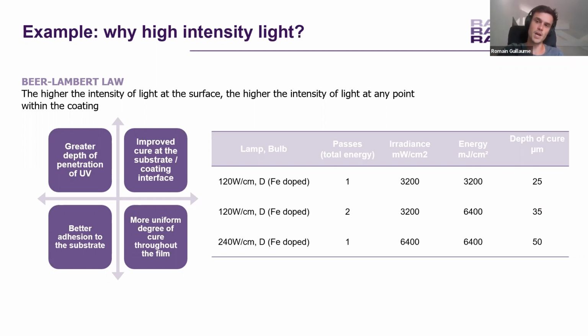But now, for the same energy, if I go to the third line, I'm taking a lamp which is 2 times more powerful, and I'm going below it only 1 time. The irradiance is 6,400 milliwatt per square centimeter, so 2 times the irradiance of the previous lamp. So I have a higher intensity. At the end, my energy is equivalent to the second line: 6,400 millijoules per square centimeter. But for the same energy, I had a higher irradiance, so locally my photons were able to go deeper in my substrate. I reached a depth of cure of 50 micrometers.